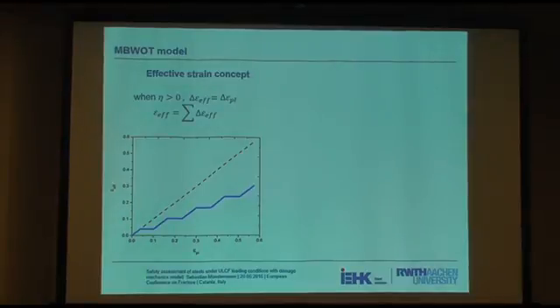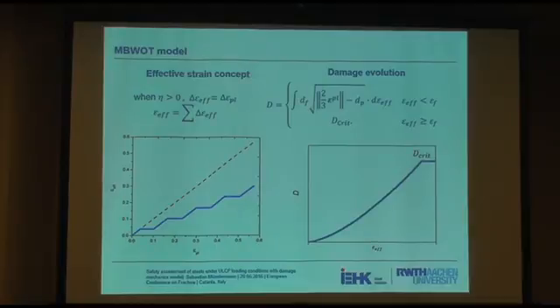So we have defined an effective strain measure. Very simple one, by the way. There are, to my knowledge, even more sophisticated ones in literature. Here we only said that our equivalent plastic strain only counts as relevant for ductile damage evolution when the stress triaxiality is positive, so when the material is under a tension load. And all the increase in equivalent plastic strain will then also serve as increase in effective strain. So in fact, if you've got a plot where you have the effective strain over the equivalent plastic strain, you see that this results in a stepwise function.